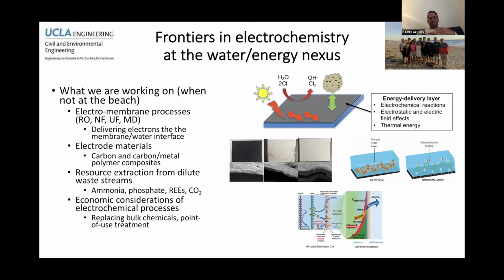The kind of materials that we work with are strictly carbon-based. We do some carbon metal composites as well, but for the most part, these are carbon nanotube-based polymer composites, where we use the polymer to cross-link the carbon nanotubes. The carbon nanotubes give us electrical conductivity. The polymers give us the selectivity. So if we want to make a desalination membrane, we will use various kinds of polyamide polymers to cross-link the carbon nanotubes. If we want to make an ultrafiltration membrane, more porous, we will use something like polyvinyl alcohol or something like that. So there's a lot of polymer chemistry involved in the formation of these materials.